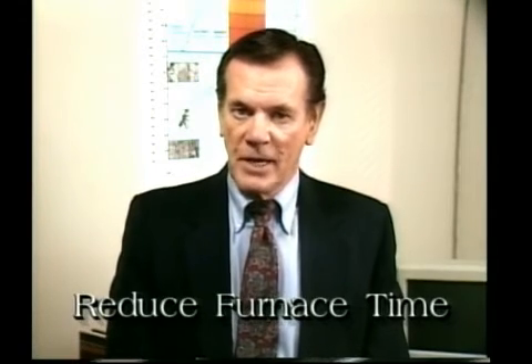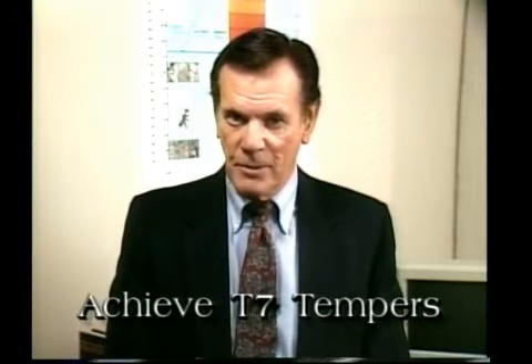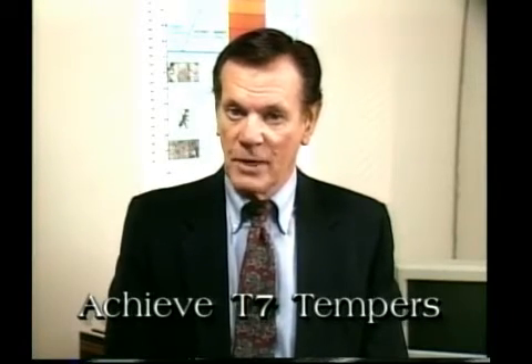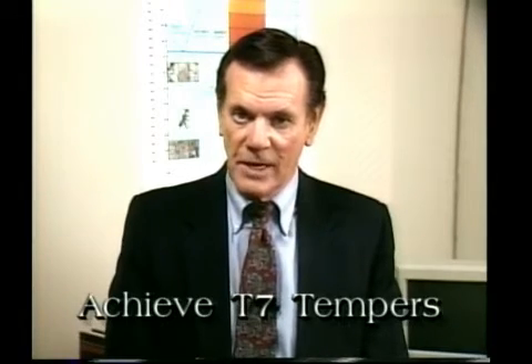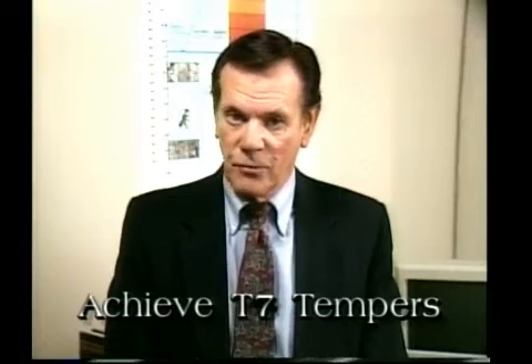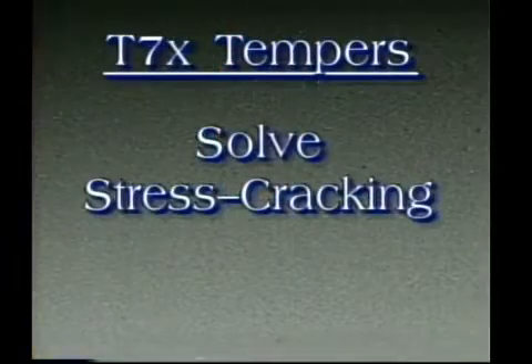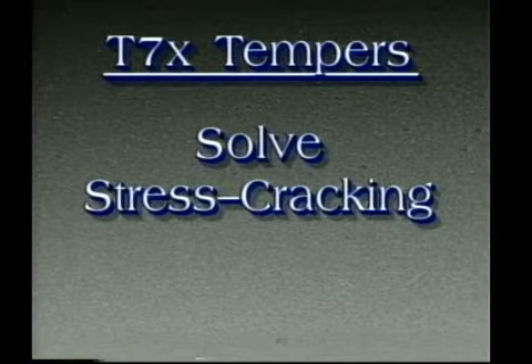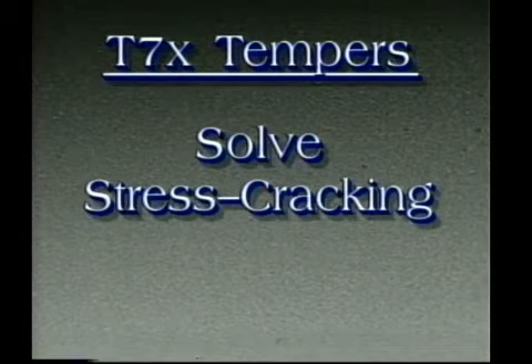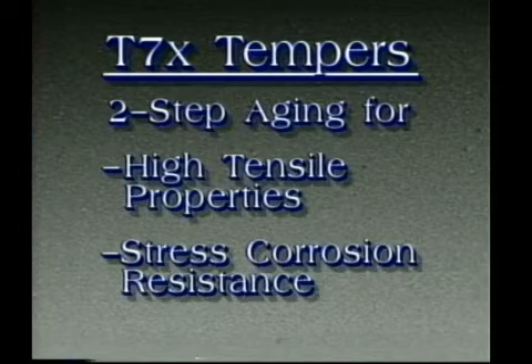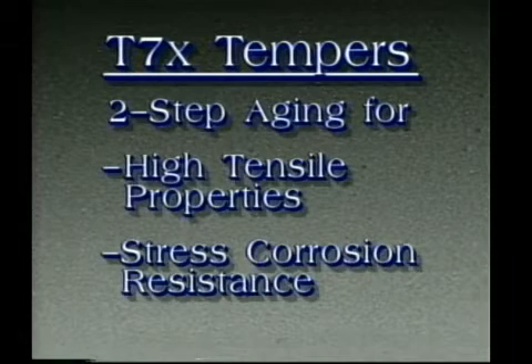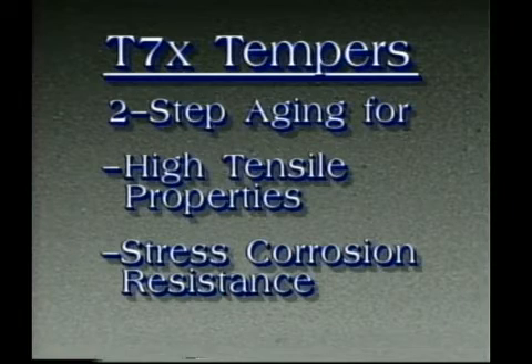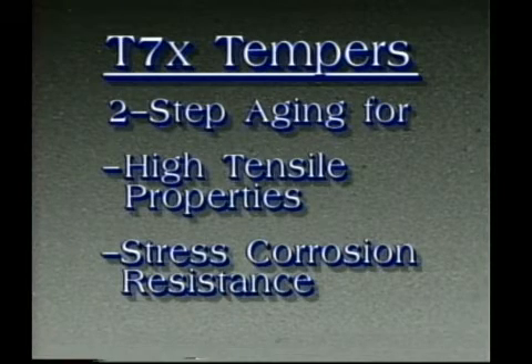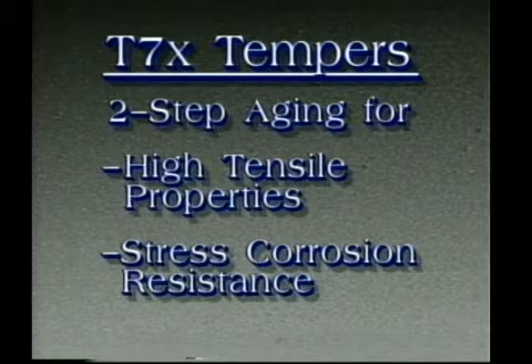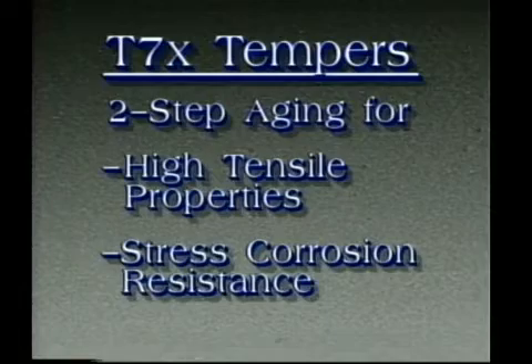More recently, step aging has been used to achieve the overaged T7 tempers, such as T73, T74, and T76 of the 7000 series alloys, such as 7075, 7049, and 7050. The step-aged T7X tempers were developed to solve stress cracking problems. It was found that the step age was necessary to obtain high tensile properties for carrying maximum loads, while at the same time making the parts resistant to problems involving stress corrosion cracking and exfoliation corrosion. It was also found that in some instances, the step age also improved other properties, such as fracture toughness.